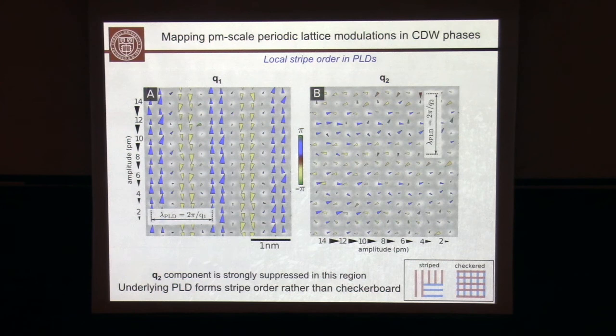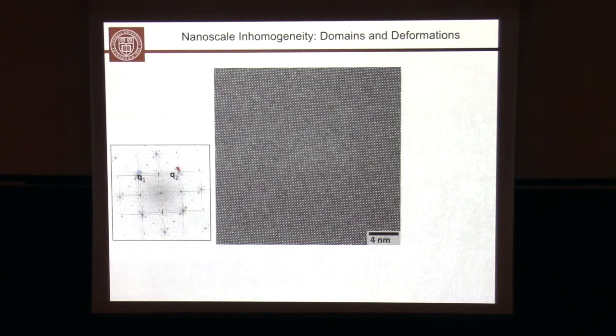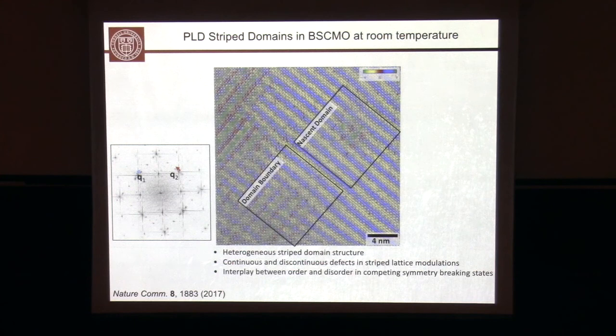Now, you might say, and it's a very valid concern, we are showing here a field of view of, let's say, 5 nanometers. What happens as you go to larger length scales? We already know, if you take a Fourier transform over about 10 nanometers or 20 nanometers, we see both modulations. So as you go now to a larger field of view, again, you need to make sure that the imaging is stable. We can extract, again, both modulations, again on the picometer scale. And now the picture that arises, indeed, we do have local stripe order, but we also have disorder. So instead of having homogeneous stripes, the stripes are heterogeneous with local defects.